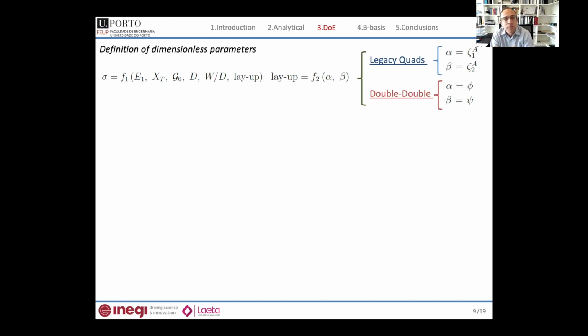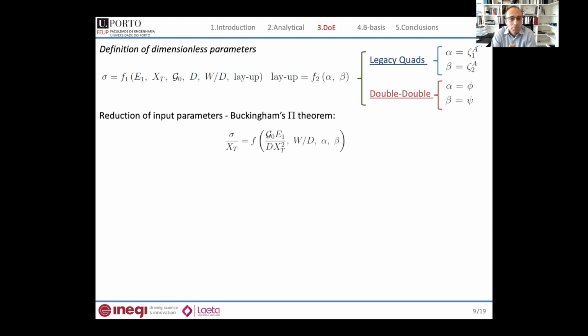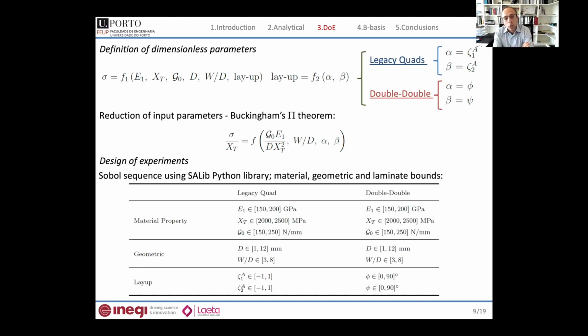We want to reduce as much as possible the number of parameters. So what we can do is very simple. We just use Buckingham's pi theorem, and we relate the normalized strength with only 4 parameters. So we are further reducing our sampling space or design space. So then we have to perform the design of experiments. So we have implemented a Sobol sequence using a SALib Python library, and we have here in this table the material, geometric, and laminate bounds. So we have typical values for the relevant material properties. We have defined geometric bounds as well, and then these are the possible ranges that both the lamination parameters and the fiber orientation angles can take.